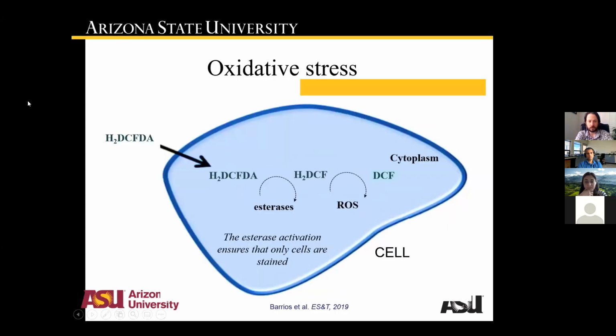So basically, we start with the H2DC-FDA, which is the reactive oxygen species indicator. This is a permeable dye that crosses the bacterial cell wall. But upon esterase enzymes present on the cell wall of the bacteria, we actually create this fluorescent compound, the DCF compound, and that's representative of the different reactive oxygen species that are present in the cell. So that's how we can see the signal of the reactive oxygen species generation.